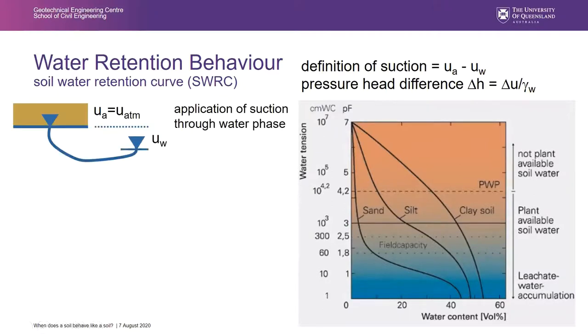The way we measure this curve is either by applying a suction through the water phase, and the difference in the height of the lower end of the water of the sample and the water column we apply is then the suction we apply on the sample. I will show later an example on that.